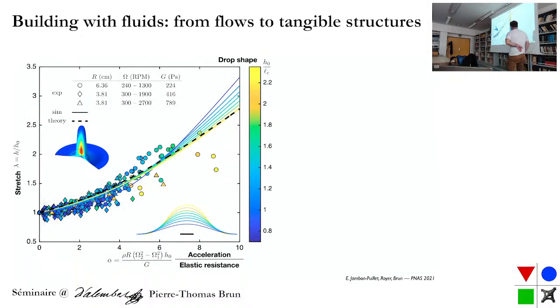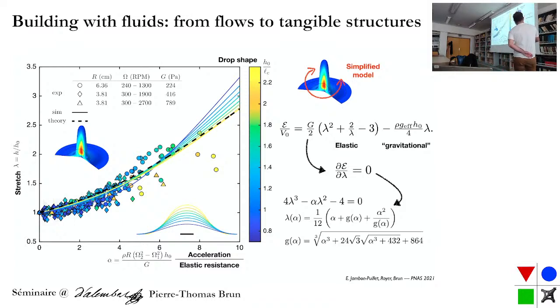Okay, so you can plot essentially how much you're stretching as a function of a dimensionless parameter, which represents essentially the ratio between the acceleration you impose and the elastic resistance. And so you see that things collapse more or less. They don't perfectly collapse because basically you stretch more if you're bigger, right? No, actually you stretch more if you're smaller. Sorry, the blue ones, they stretch more than the yellow one. But if you forget about this and you can try to predict essentially more or less this trend, what you can do is say, okay, I have something which is a piece of rubber. I can write the energy by writing an elastic component and some sort of gravitational component. I minimize that and I find some ugly formula, but this ugly formula seems to work pretty well.